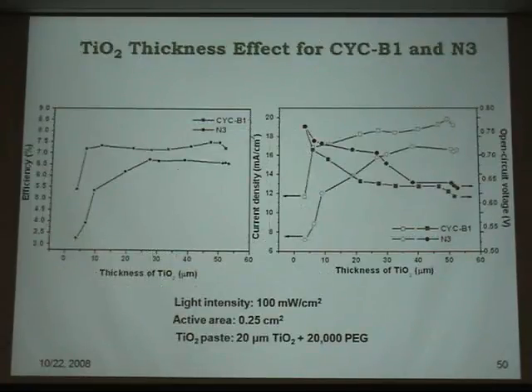Now, in terms of thickness effect, it does play an important role. For the N3 dye, you need to have a 3 or 4 coating to get enough cell efficiency. But for our homemade dye, you only need 2 coatings to reach the saturation of performance. This is just another version of efficiency in terms of current and open circuit voltage.